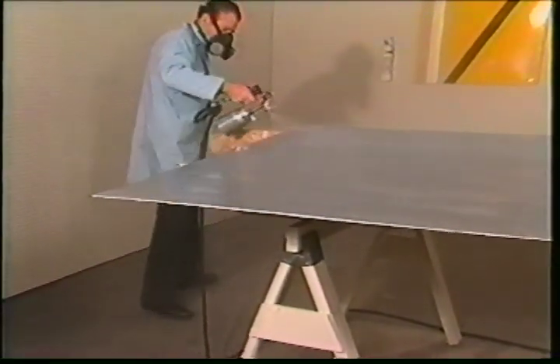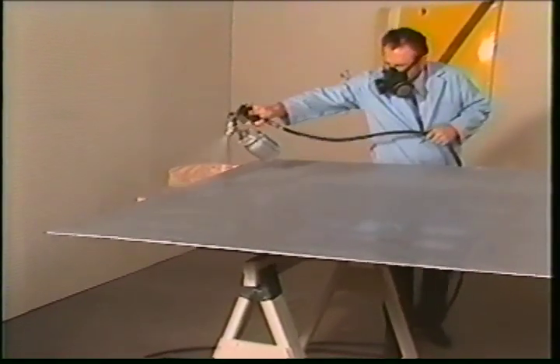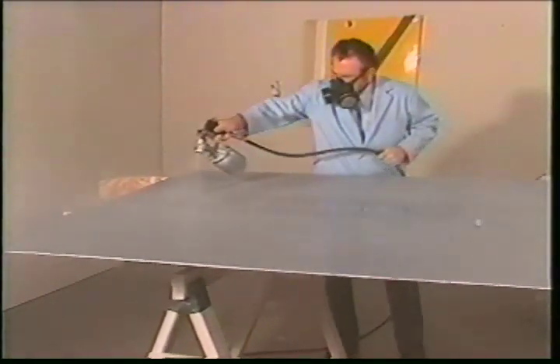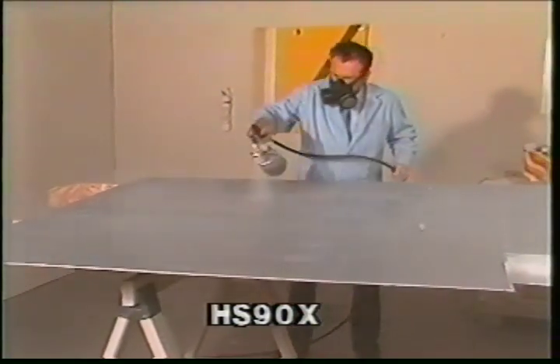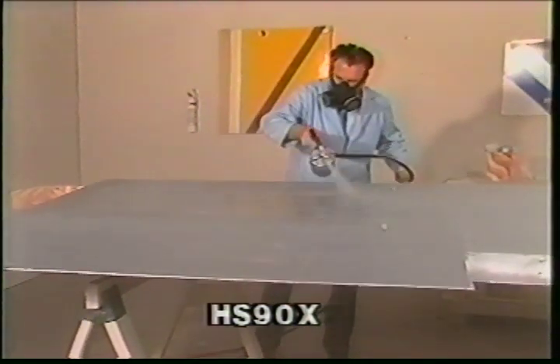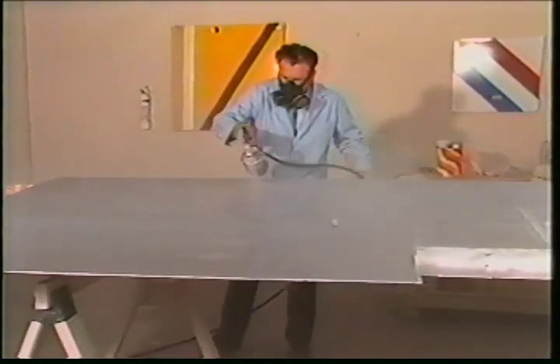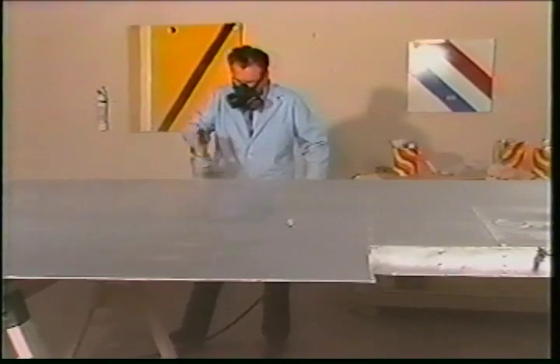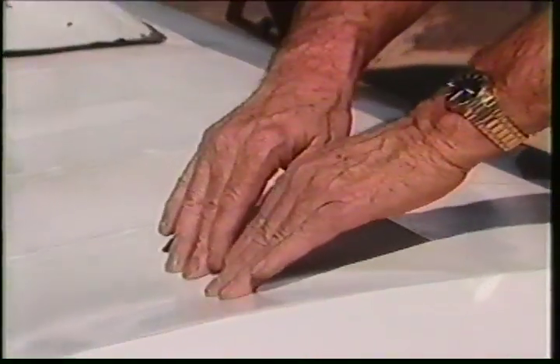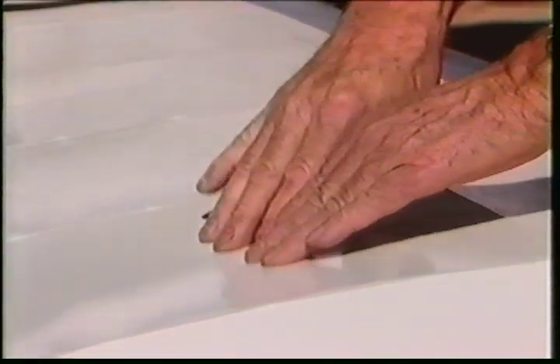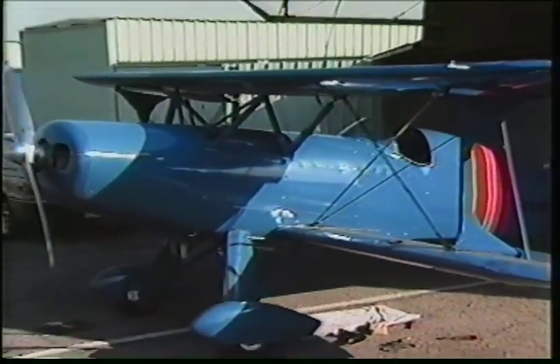Coarse weave polyester styles usually require 4 or 5 coats to develop a suitable base for a smooth finish. However, the finer weave style, HS90X, is ready for the finish coat after the 3rd poly spray application. The completed coating system should fill the fabric weave. However, we strongly recommend that the coating buildup not completely hide the fabric weave or the tape edges, because excessively thick coatings may separate by tension when the fabric is pressed around the sharp edges of ribs, stringers, and fuselage structures. The polyfiber coatings are flexible and non-tauting, but must retain a certain amount of toughness to resist scratches and abrasions. There is a limit to stretching at any one point when pulled around the outside of a sharp radius.